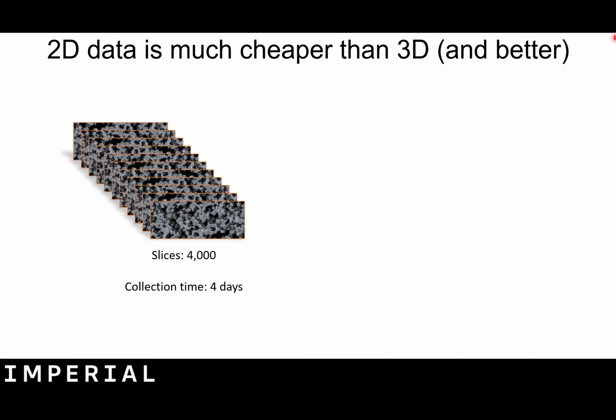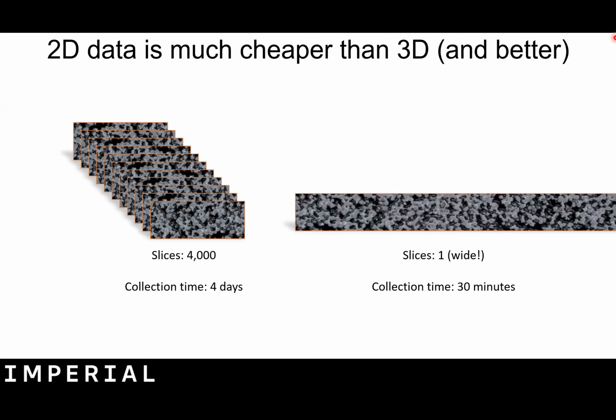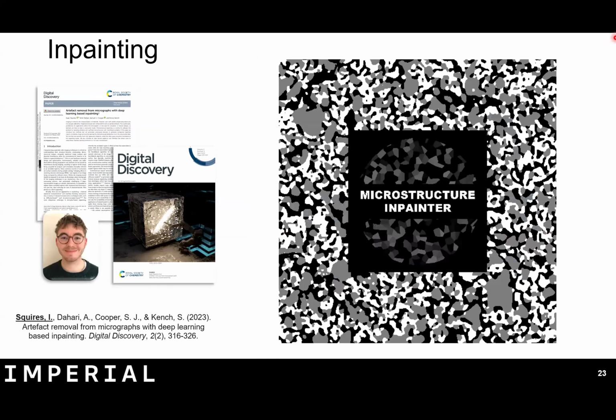So you need to image them with FIB-SEM, but FIB-SEM is very arduous, right? Even when you are a master, it still takes a long time. And so getting a representative volume in 3D could take you 3 or 4 days on a £2 million microscope. Or a single wide cross-sectional image that's just 2D can be collected in about half an hour on the same microscope. So it's a 2 order of magnitude speed up in acquisition time. And then you use this single 2D image to train a 2D to 3D generator, and you've got what you need.